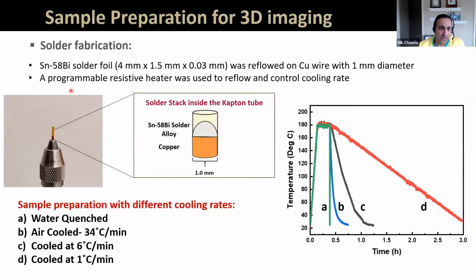You have a solder foil, which is essentially melted on a copper wire. This copper wire is about 1 millimeter in diameter. And we looked at different cooling rates. Some are water quenched, some are air cooled. And these are essentially put on a resistive heater to control the temperature. And so the temperature profile looks something like this. Going up, get to the melting point, and then we cool it down.